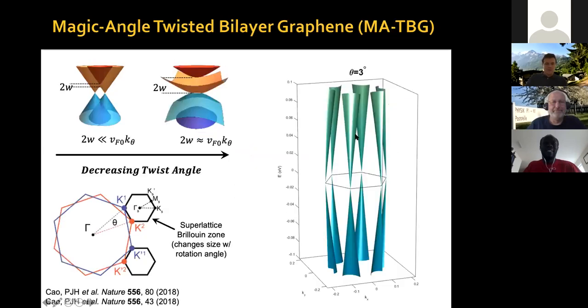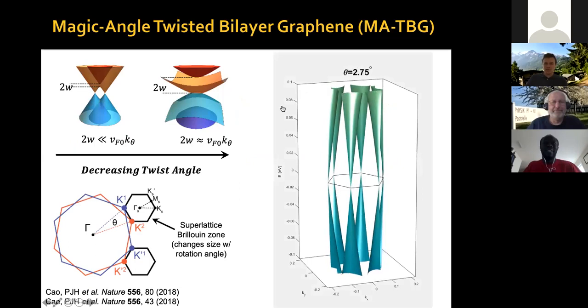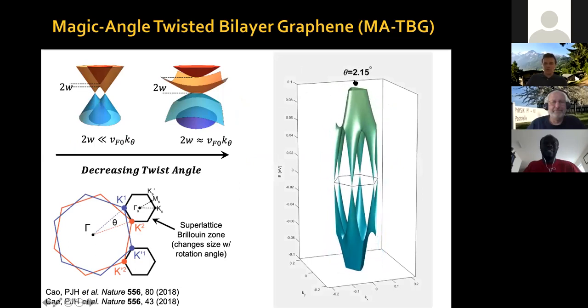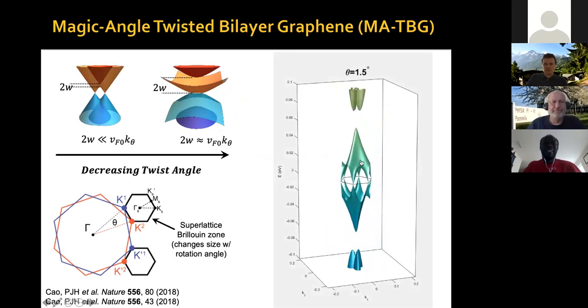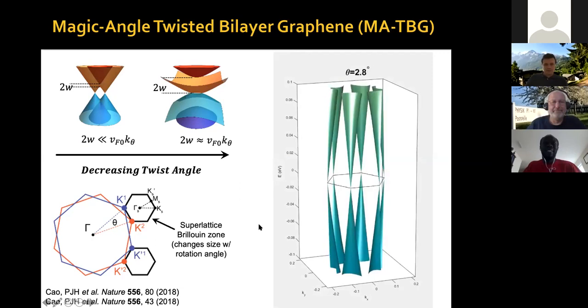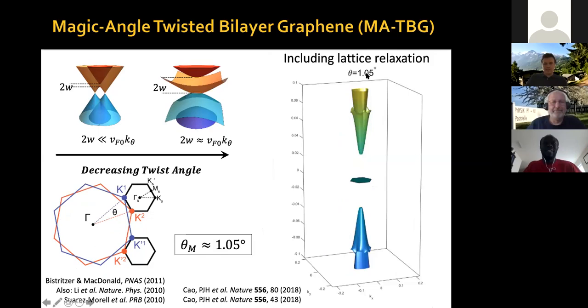Now, again, let me just run this video. This video shows the evolution of the electronic structure. This is a cartoon, so the evolution of the electronic structure as you rotate the angle from 3 degrees towards the magic angle. What you can see is that within this energy window, as you go below about 2 degrees, there's a major reconstruction with this set of bands separated by band gaps. These bands become flat at 1.1 degrees, and then there is a more complex evolution. Now, including lattice relaxation, this number may vary a little bit above and below, but the basic thing is that you have these flat bands.